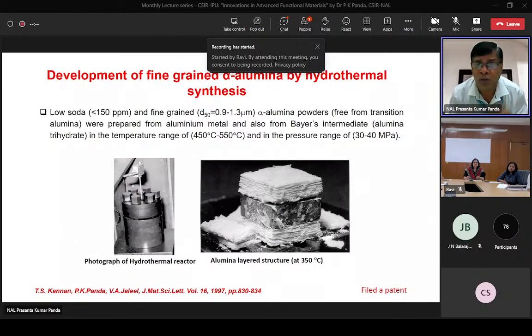And in the process, it will also be transforming into theta, eta, zeta, gamma, a number of transition aluminas. So finally, you may not get a highly pure form of alpha. But this process was generating alpha alumina at 500 to 550 degrees centigrade, compared to the 1600 degrees required otherwise, but there is a pressure element. About 30 to 40 MPa, which is not applied from outside, but is autogenous.